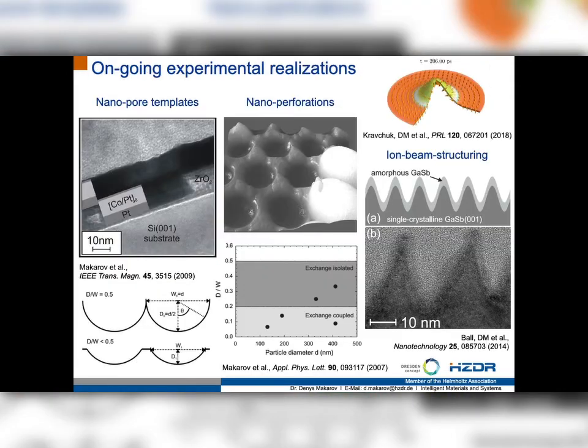Of course, you can imagine that there are a lot of activities in the experimental community to work on the realization of such curved objects, where you can use nanopore templates, perforations, the deposition on curvature templates prepared by spherical particles, or ion beam structuring, where you can really nicely tune the exchange coupling between the neighboring cap structures. So you can really expect very soon the experimental confirmations of all these exciting effects with localized Skyrmions in curvilinear geometries. I'm very much looking forward to these investigations.